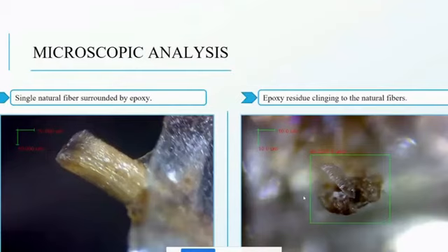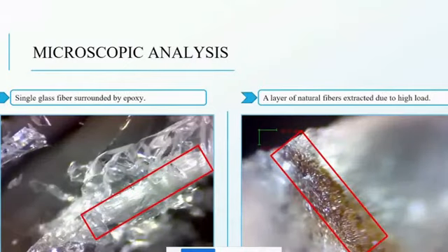Finally, some of the microscopic analysis. In this one, this is a single natural fiber surrounded by epoxy for the small punch test after the fracture. Here we are showing some of the epoxy residue clinging to the natural fiber, and this is the cross section. We need to do more SEM for this one. This is the white one: the glass fiber surrounded by epoxy after fracture. This one we try to show for the orange one.